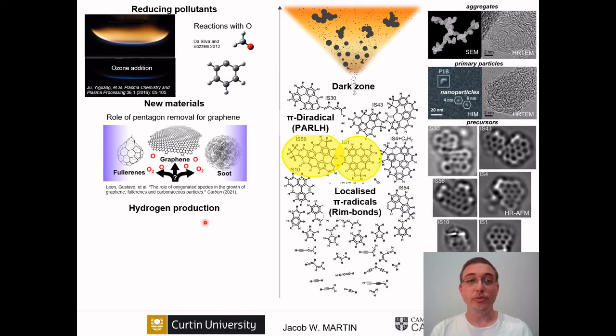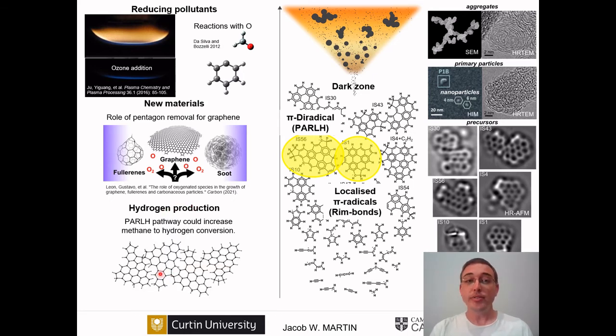Secondly, if we can remove the pentagons selectively, then we can stop soot from forming and grow graphene. And there is some evidence that we've found in microwave reactors where large graphene can grow when you get enough oxygen atoms to etch the edges. And finally, we're very interested in how we can use this new pathway to enhance the conversion of methane into hydrogen. So thank you very much for listening, and I welcome any questions.